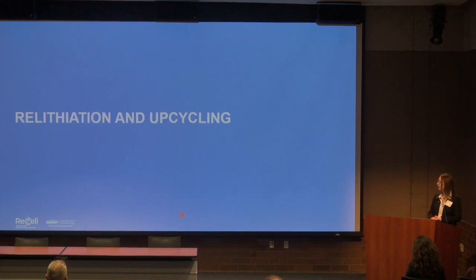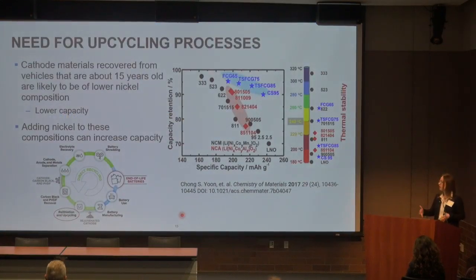So this brings me to a project that I started on in the last year and a half, looking at both the relithiation and upcycling of cathode materials. So why do we need an upcycling process? I keep reiterating that you need to make these processes profitable, right? And if we're getting cathode material or these batteries at the end of life, they're already about 10 to 15 years old at that point. So looking back, those chemistries are probably no longer relevant for energy storage needs for electric vehicles today. Looking back 10 to 15 years ago, that means it's a lower nickel cathode compared to the higher nickel cathode used today. So we find that by adding more nickel into this end-of-life cathode material, we can reach a higher nickel composition and then alternatively reach a higher energy density. So this is the definition of upcycling currently, but this will continuously change as our feedstock changes. That's one of the largest difficulties with recycling, right? The feedstock is continuously changing.